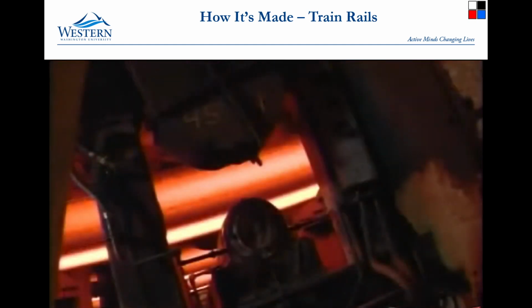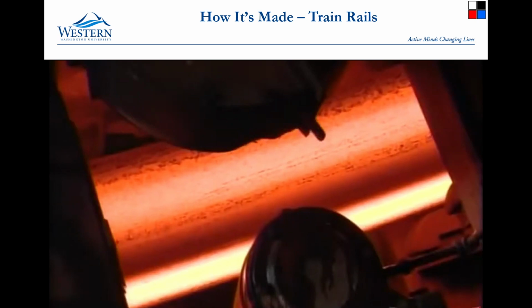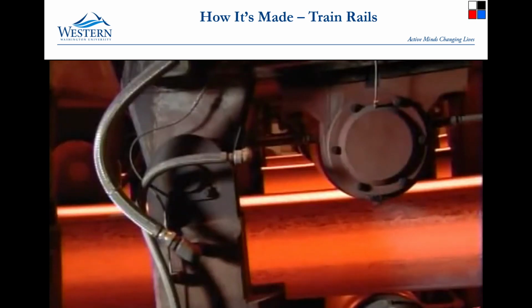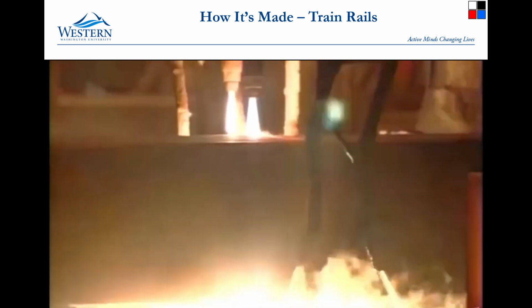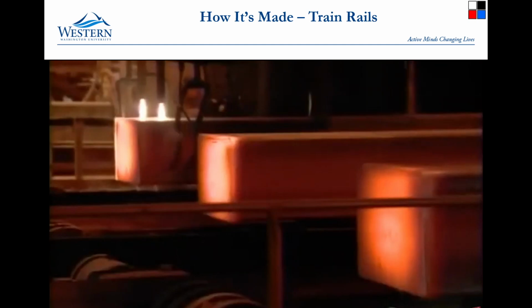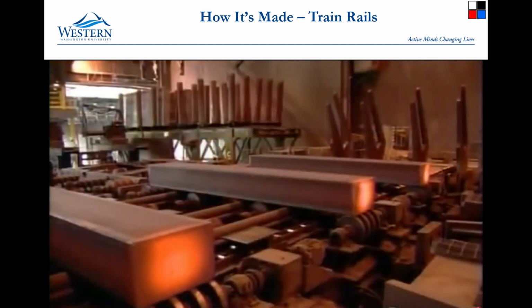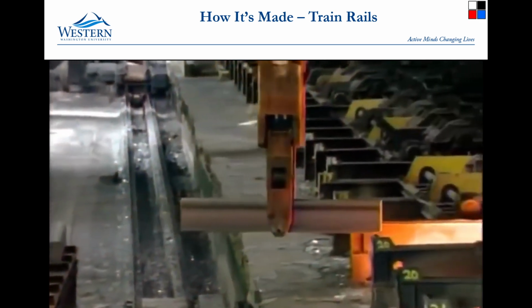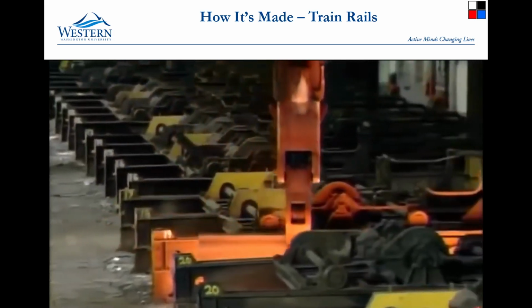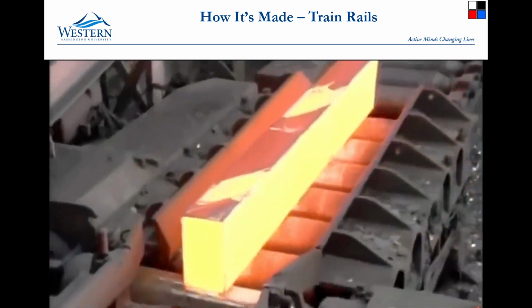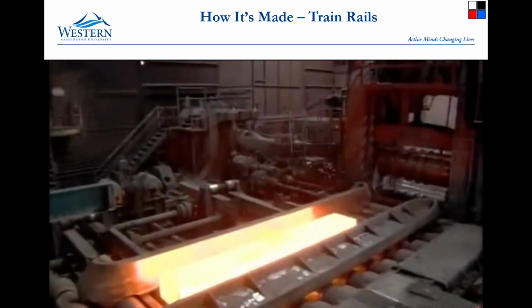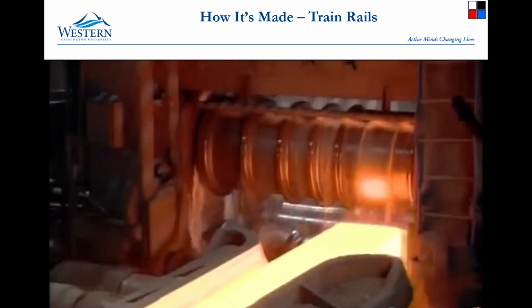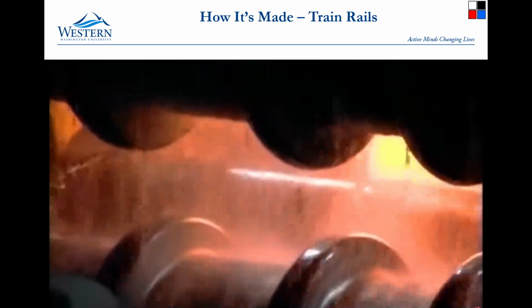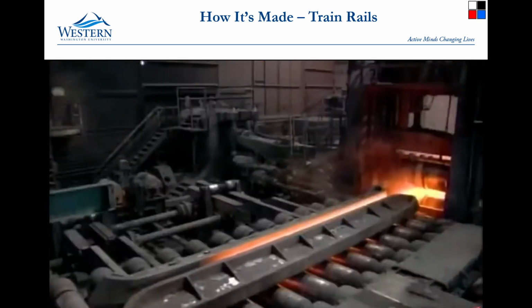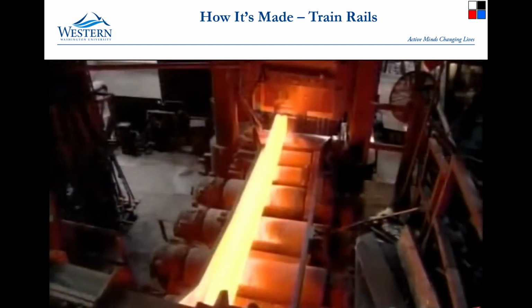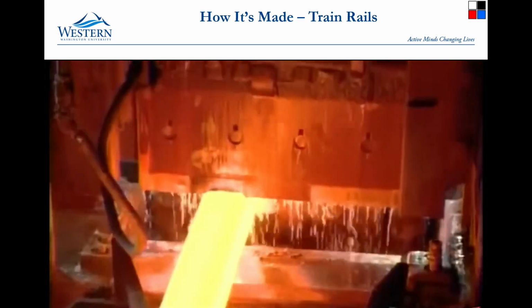The alloy then runs down a ceramic tube that shields it from exposure to oxygen, which would ruin the metal. From there, the molten metal flows into molds which extrude it into continuous rectangular blocks called blooms. Acetylene torches cut each bloom into 3.5-meter lengths. A crane then transfers the blooms to a furnace, which, over the next 5 to 7 hours, reheats them to 1250 degrees Celsius. This softens the steel for further shaping.